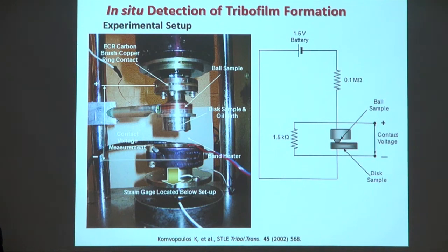Usually sulfates are conductive. Phosphate phase is insulating. Borate is also insulating. So if the film contains phosphates or borates, it should give me a high contact voltage, and it will give me an increase of this contact voltage when the film begins to form. If it doesn't contain any of these, and I have incorporated those in the film as additives, that means that the reaction did not occur and the tribofilm did not form. Or it was removed much faster than it was trying to form by the wear process.